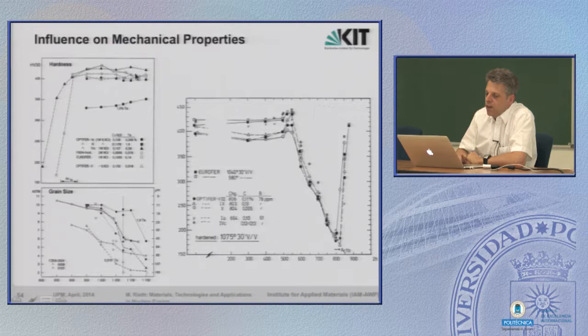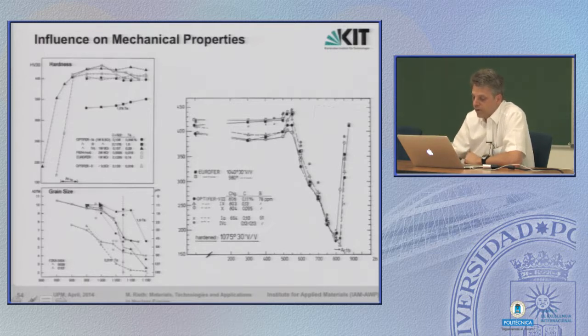That's quite hard. And regardless of the temperature, 1100 or even 1150°C, you always produce martensite with the same hardness. The only effect it has is on the grain size. This is plotted here. Grain size increases along this line. Here, lower points mean larger grain size. And grain size means austenitic grain size. And this austenitic grain size becomes very, very large only at temperatures above 1100°C. So usually you avoid this high annealing area and do the austenitization around 1000 or 1100°C.